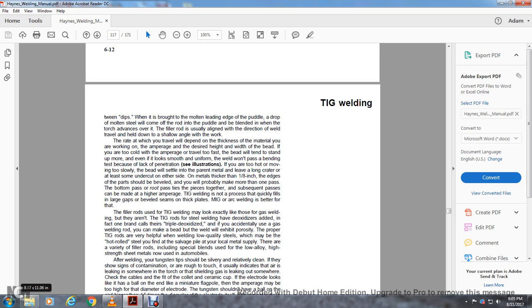leaving a long crater, and at least some undercutting on either side. On metals thicker than 1/8 of an inch, the edge should be beveled. You will probably make more than one pass. The bottom pass, the root pass, ties the pieces together. The subsequent passes can be made with a higher amperage.